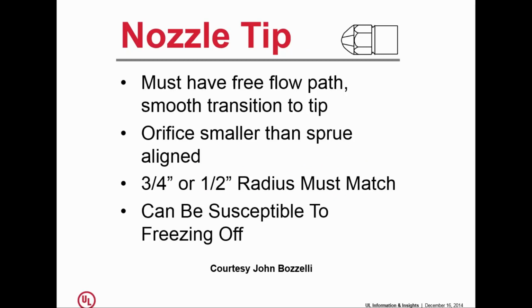And the fundamental thing that makes this a challenge is the fact that this nozzle tip is up against a piece of metal with pressure applied that is probably 300 to 400 degrees Fahrenheit cooler than the material that's flowing through it. And so it's naturally an area susceptible for freezing off. This is an area we really have not done a lot of work on. Most of the time, we all know what we do if we're processors. We put a piece of cardboard in there, and we hope to heck that reduces the amount of heat transfer between the nozzle tip and the sprue bushing.